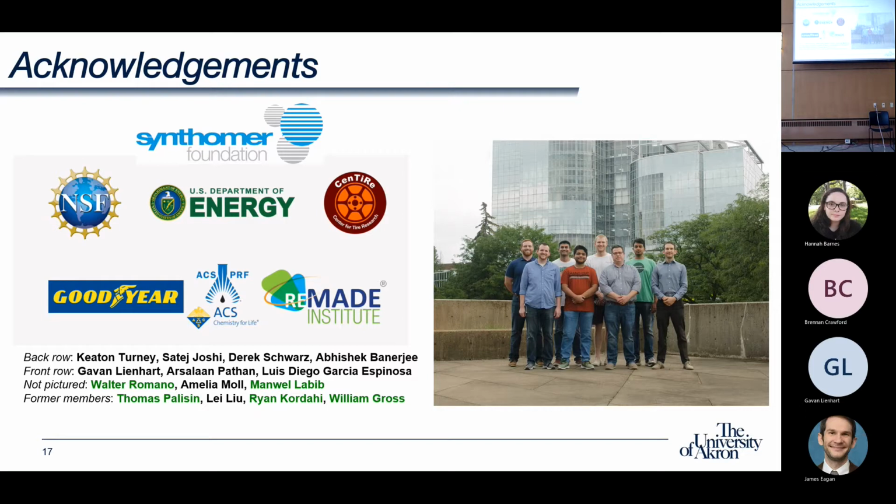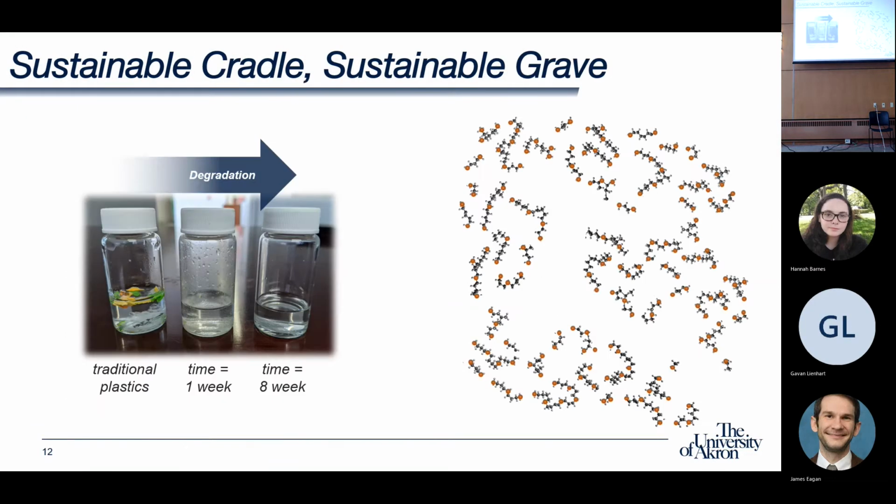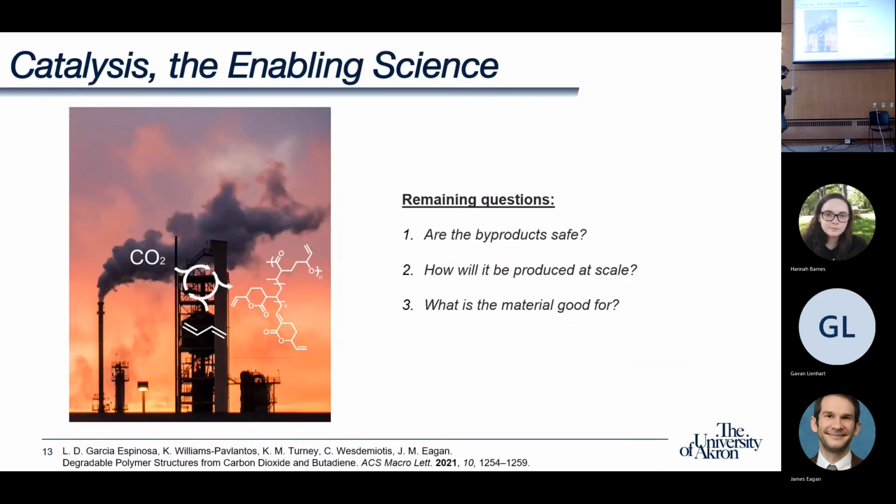I have a question. What's going on with the polymer chemistry that it's breaking down if you're using atmospheric CO2? So when we show this cartoon, not a lot of information in there. The CO2 linkages and the real technical aspect behind this is that if you take a monomer for a polymer, typically an olefin, like butadiene in this case, or ethylene or propylene, if you make a polymer out of that, you get an all-carbon backbone, completely non-degradable, will last for centuries.